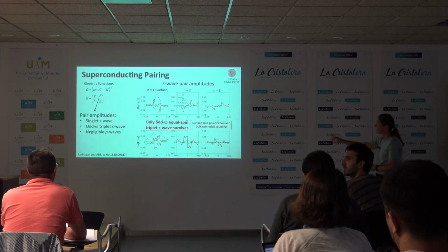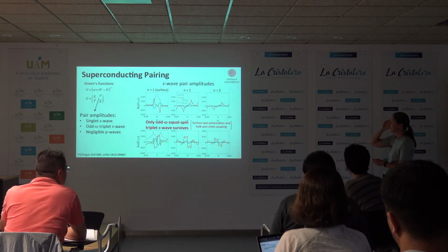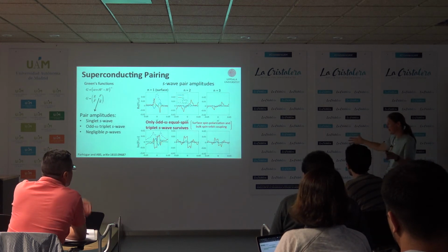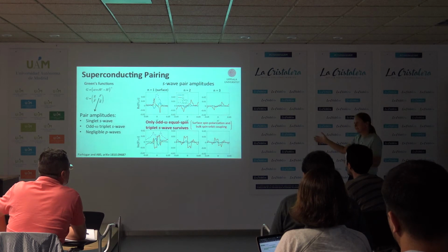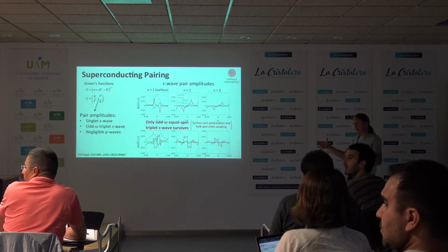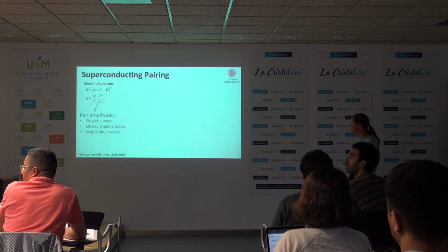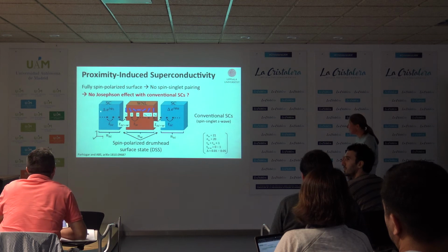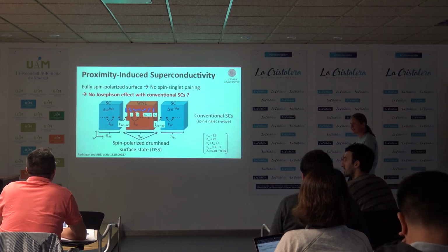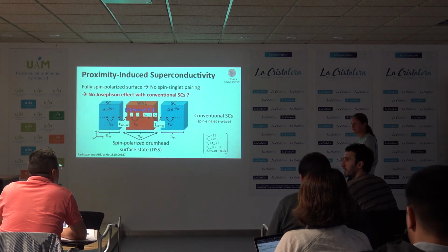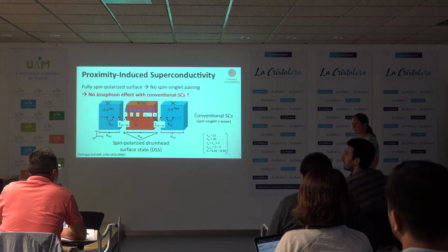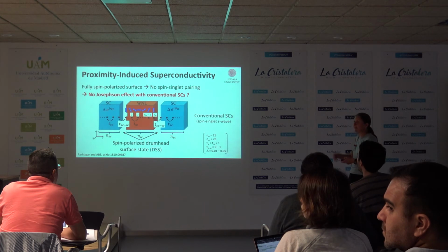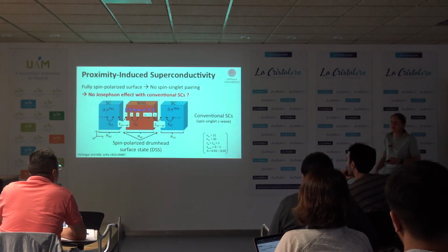So this will happen because I have some inhomogeneity. In this case I have inhomogeneity in real space. But it's real space, not time domain. Yes, but that propagates through. So I have a superconductor and I propagate the Cooper pairs into this material. There's no order parameter in here. The order parameter sits out here. So you will have a frequency dependence even in an SN junction.